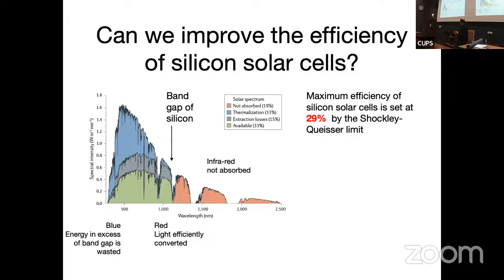on the blue side, the light's absorbed, but the electron you promote into the conduction band will just drop down to the top of that band, the bottom of the band gap, and that energy will be lost just as heat. So the only place that a silicon solar cell can approach full efficiency is exactly for energies at the band gap, and this is what means that you can't exceed this limit. 29% is as high as a silicon solar cell can ever go.